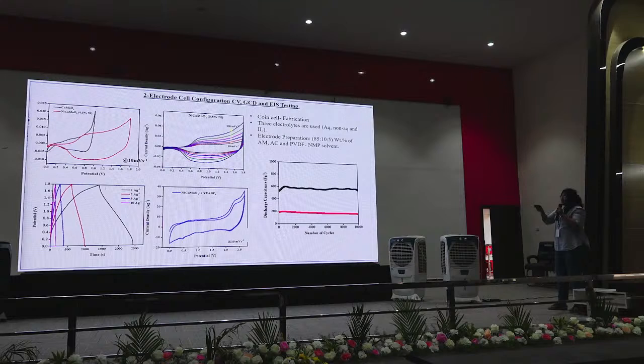The third graph is about all the current densities of the nickel cobalt molybdate. In all of these the electrolyte is 6 molar KOH. The fourth graph is about the organic liquid electrolyte. All the other potentials are around 1.6 and 1.8, but the potential here increases to around 2.5. This is because of the electrolyte.